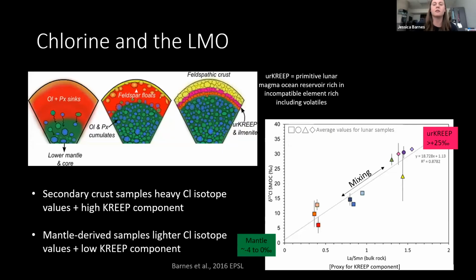So realizing this, the trend that we see between the chlorine isotope compositions and the trace elements is telling us that urKREEP, the primitive form of KREEP from the lunar magma ocean, likely had a very fractionated chlorine isotope composition of around plus 25, plus 30 per mil. And the mantle of the moon is likely characterized by unfractionated to even depleted values, maybe down to -4 per mil.